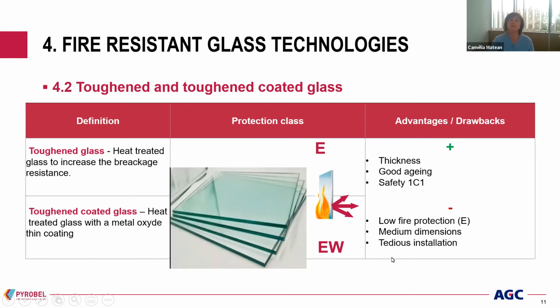But it's in the low fire protection class, with medium dimensions for application. As it's a tedious installation, it's quite sensitive. If you have during the installation the lowest scratch on the glass, then the glass will break during the first 5 minutes of the fire and will no longer be protecting.